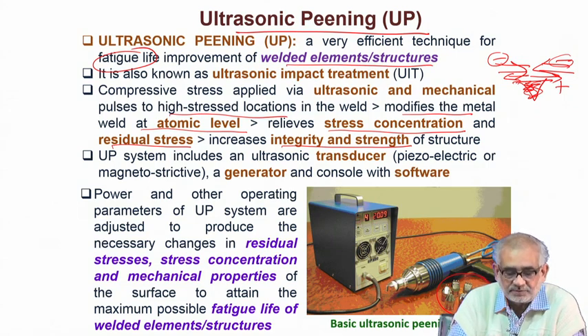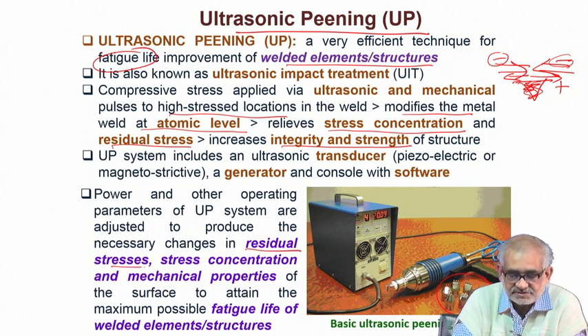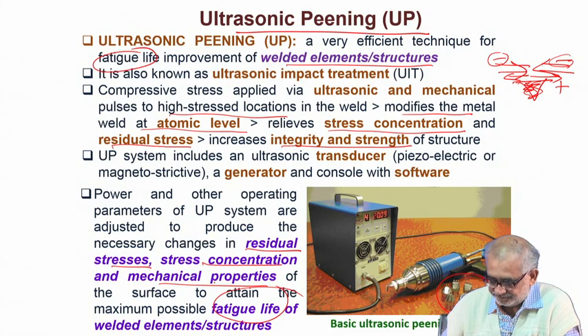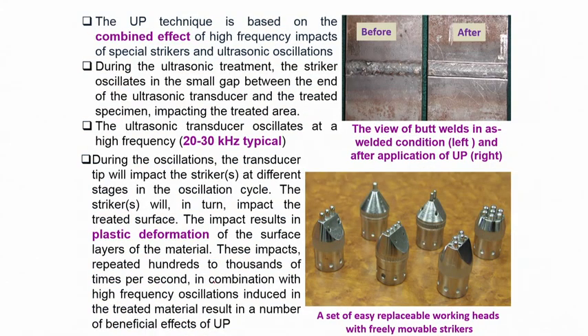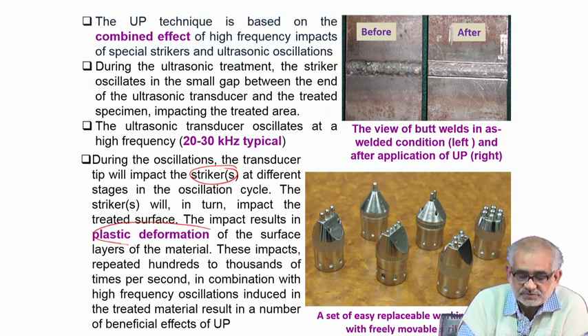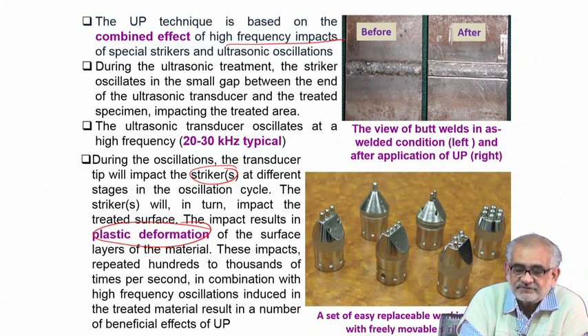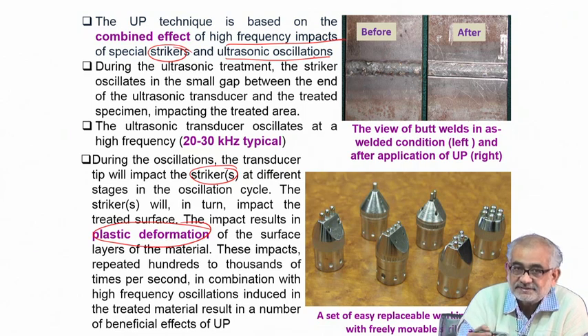By adjusting or optimizing the parameters, we can produce necessary changes in terms of residual stress, stress concentration, and other mechanical properties, thereby improving the fatigue life. The implements used here — instead of spherical shots — are called strikers. The strikers are propelled by ultrasonic waves at very high frequency and are responsible for the creation of plastic deformation.